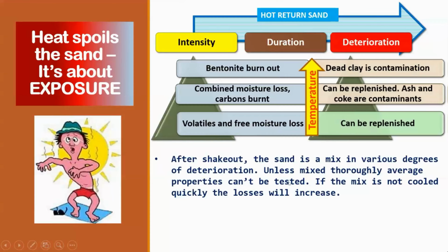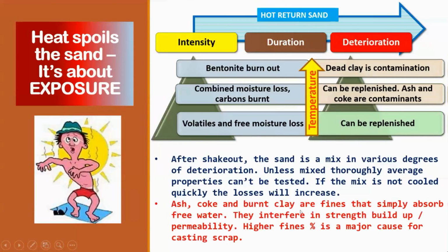So you need to cool it quickly, that is one. The second is you should mix it thoroughly before testing it. Ash, coke, burnt clay or fines simply absorb free water. They are just like blotting paper. They interfere in strength buildup, interfere in permeability of the sand. Higher percentage of fines is a major cause for casting scrap.